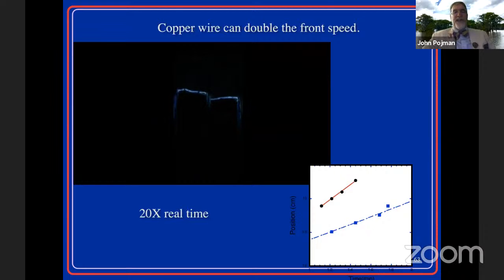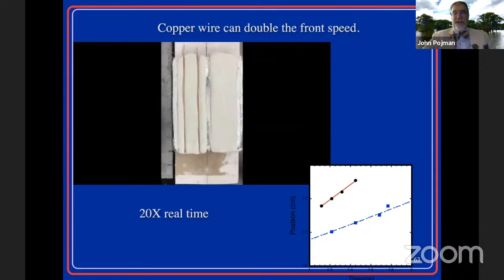And here we found that just by putting a copper wire in it, we can make the front double its speed. And current studies have shown you don't even need a wire. You can just use a very thin sheet of aluminum foil and you can make the reaction double in speed. So that's an advantage because you want to reduce some of the expensive components of the system, but still get a rapid reaction.